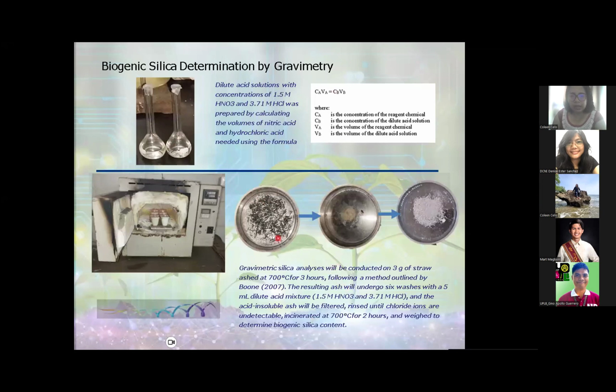So this is the burning process. Gravimetric silica analysis is conducted on 3 grams of rice hull ash at 700 degrees Celsius for 3 hours, following a method outlined by Boone. And then the resulting ash will undergo 6 washes.